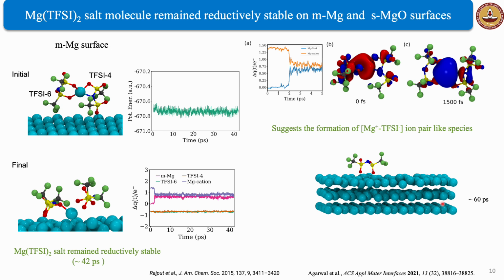Next, we also analyzed the stability of the isolated TFSI anion on the metallic Mg surface, and we found that over the course of a 60 picosecond NVT simulation, there is no charge transfer and no decomposition of the TFSI anion. We also checked the influence of an electron-rich environment. For that, we added an extra electron to the system and ran the simulation for an extra 15 picoseconds. There also, we didn't observe any decomposition of the TFSI anion. Taken together, our findings suggest that the Mg(TFSI)2 salt, the Mg+ TFSI- ion pairs, as well as the TFSI anion themselves exhibit poor reactivity on the pristine metallic Mg surface and remain reductively stable.